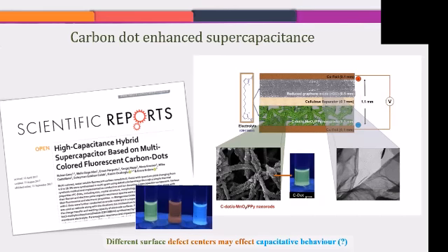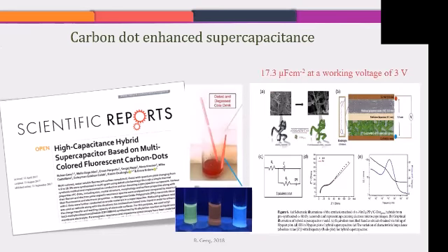We covered manganese electrode with carbon dots, and on the other side we use reduced graphene as a second electrode. And by this way, we achieve really high voltage, really high photocapacitive efficiency with 17.3 microfarads per centimeter square. So this was very great work. We start with that and we continue, of course.